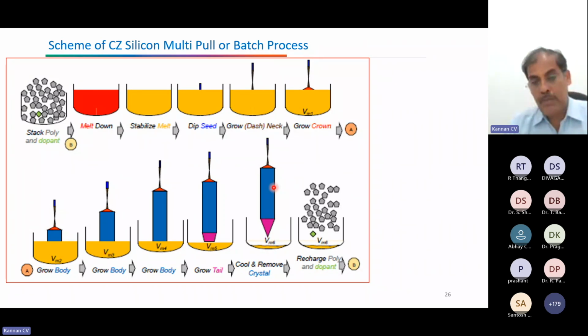Earlier, maybe a few years before, once you completed this crystal, you had to stop the complete furnace, take the crystal out, remove the crucible, put in a new crucible, and load it again. But recently, instead of using the crucible only one time, you can maintain some volume here. Instead of taking out 100% of the melt, you maintain 30% or 40% of the melt volume. Then you take the crystal out, put in the material again, start melting, and put in another seed again. So by using the same crucible, you can grow 4 or 5 crystals.